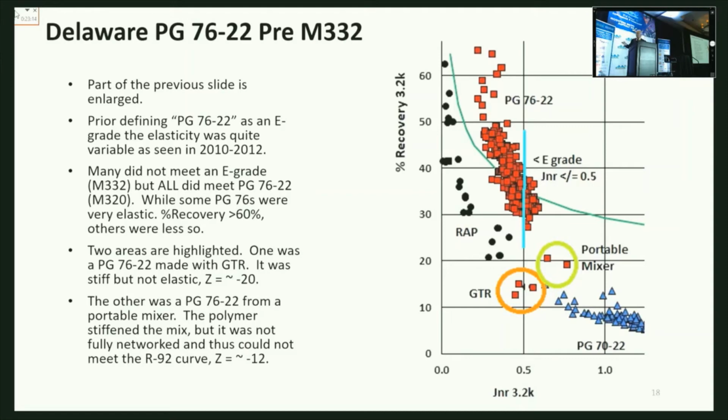Now what's happening? If you look, I mean, tires are bouncy, you can bounce tires, and rubber's bouncy, but why isn't this elastic? You look at the ground tire rubber particles in asphalt as raisins in raisin bread. It may make it stiffer, but what you're measuring for your percent recovery is not the raisins, but the bread, the continuous phase. The continuous phase happens to be your base asphalt, which is some unmodified asphalt. And so your percent recovery in your MSCR basically looks like an unmodified binder.